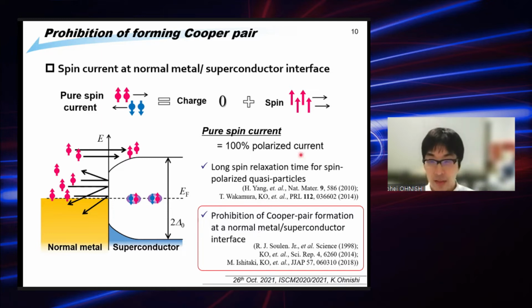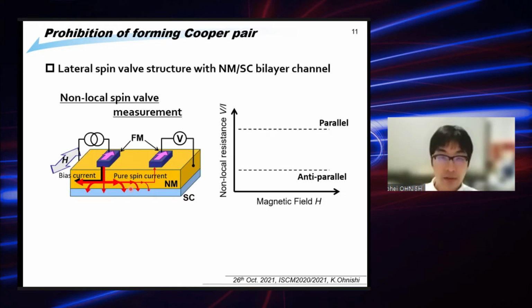To measure this prohibition of Cooper pair formation at the interface for the pure spin current, we use the non-local spin current measurement. In the non-local measurement, we use another ferromagnet as the detector. The point is the non-local resistance measured in this probe configuration. The non-local resistance depends on the relative angle of the injector and detector. In the parallel case, the non-local resistance is in the high resistance state.